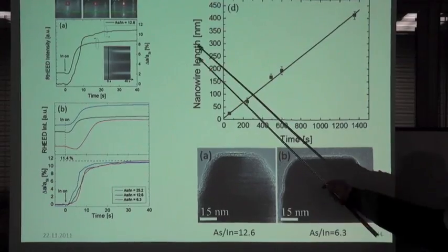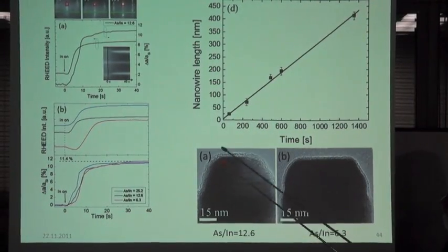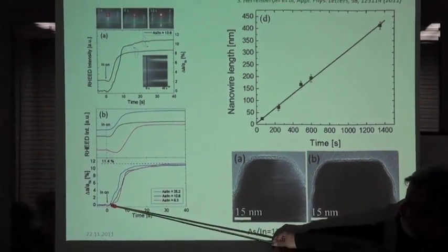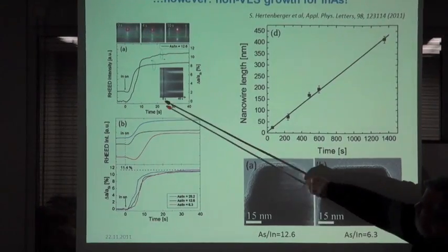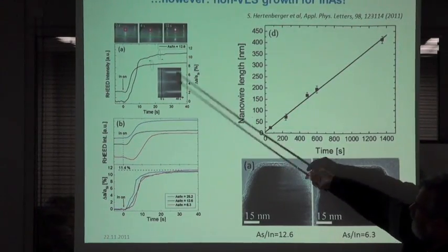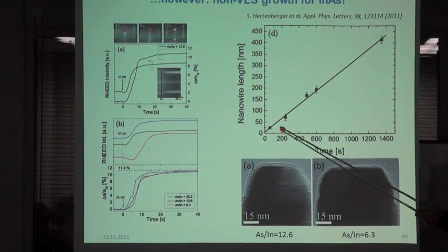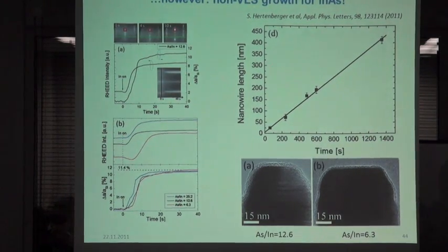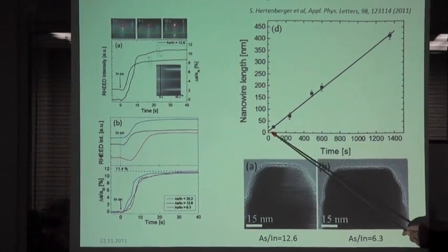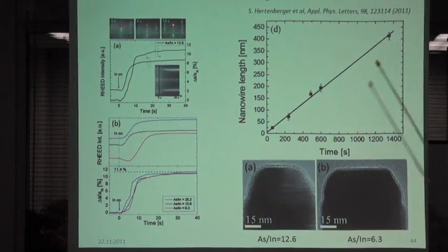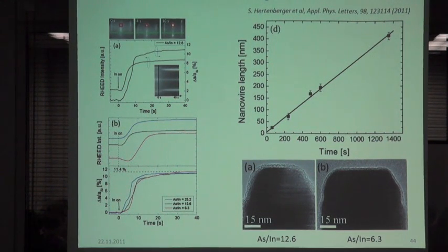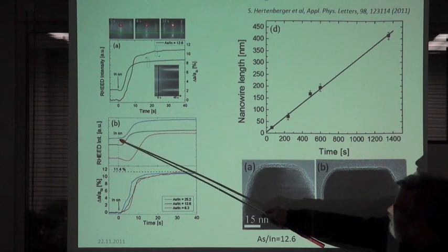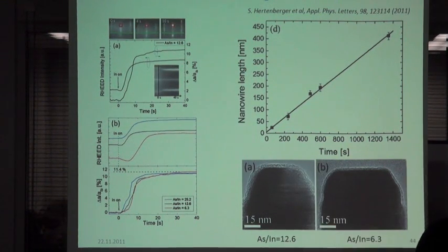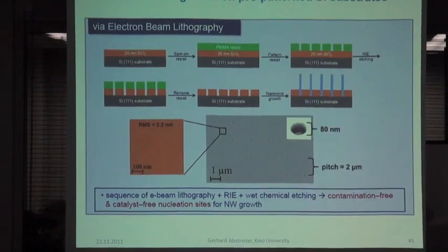But when we do in situ RHEED, what we see is that immediately after we open the indium shutter, we have already a relaxation of the lattice constant and a change, and so we have no delay. When we do this with gallium arsenide, with the gallium droplet, we have here a delay because we have to form first the gallium droplet. And for indium arsenide, it starts immediately after you open the indium shutter, you get the growth. And we have also other detailed analysis of this.